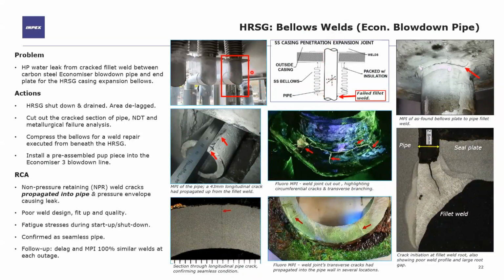On one of our HRSGs earlier this year, we saw a steam and water leak coming from one of the economizer blowdown pipes. And when it was delagged and drained, what we saw was a circumferential crack in the fillet weld between the carbon steel bellows end plate and the carbon steel pipe. This is kind of schematically shown at this tiny little black thing there.